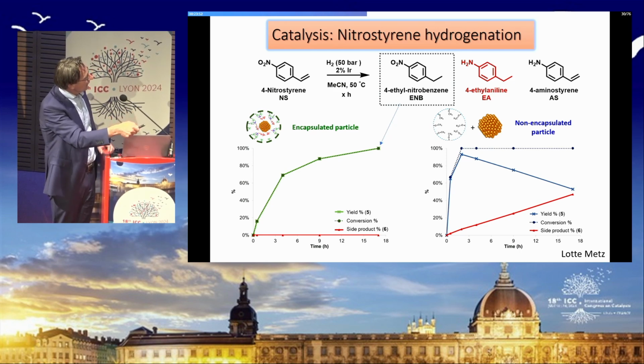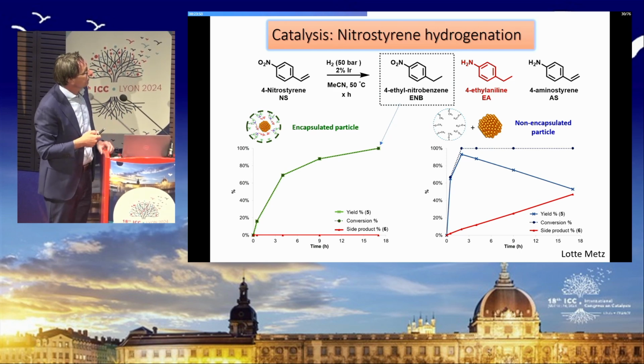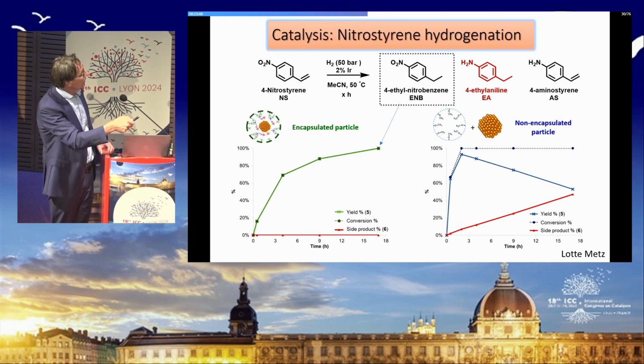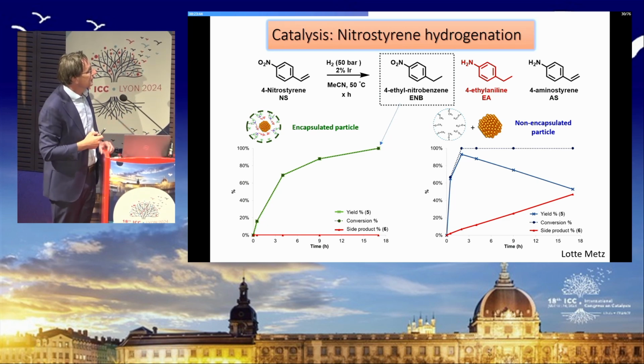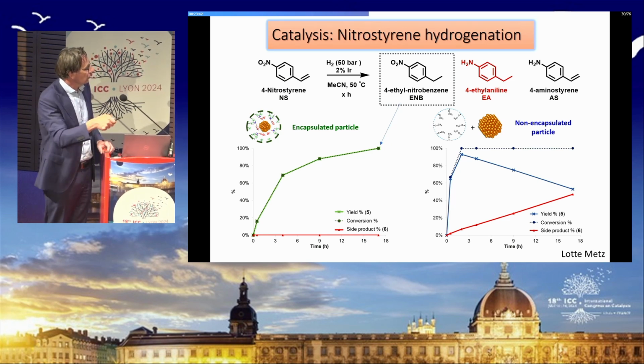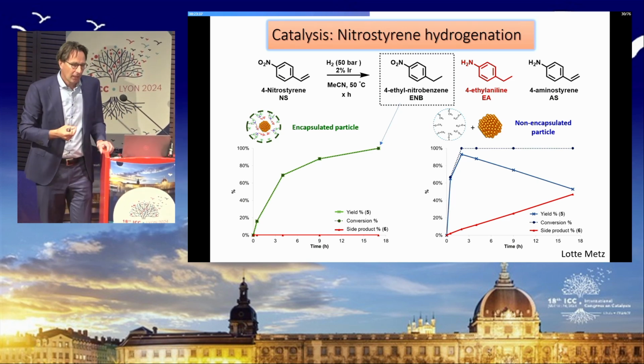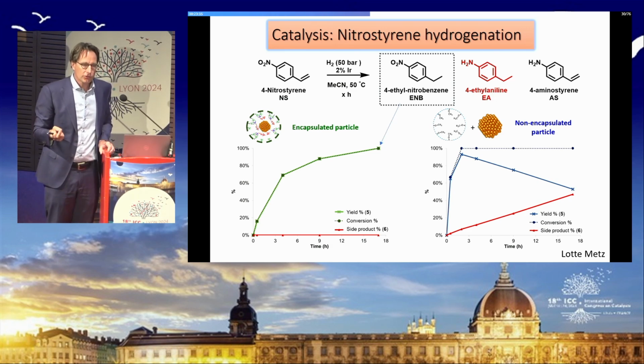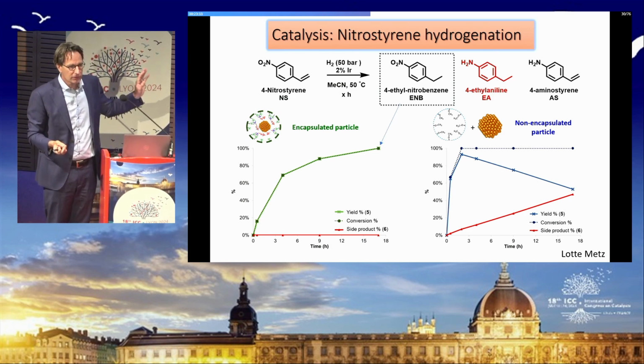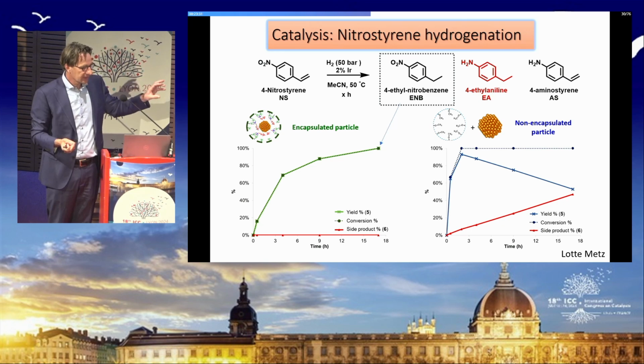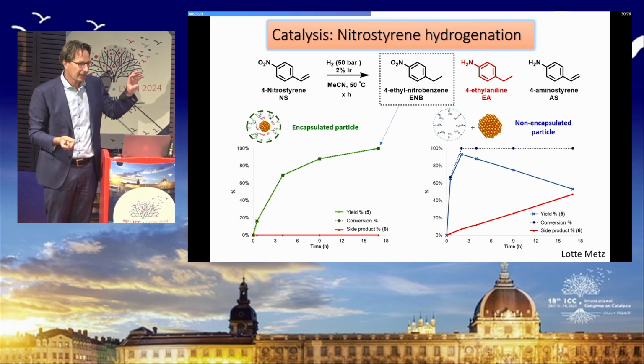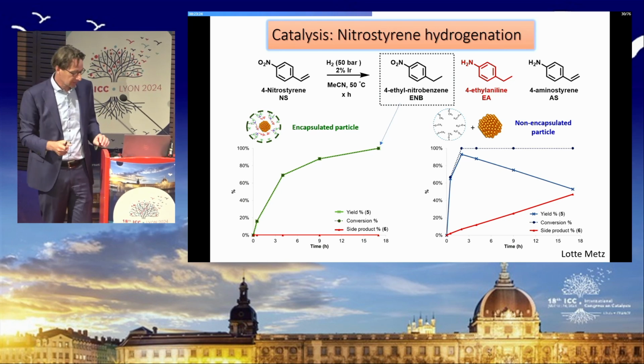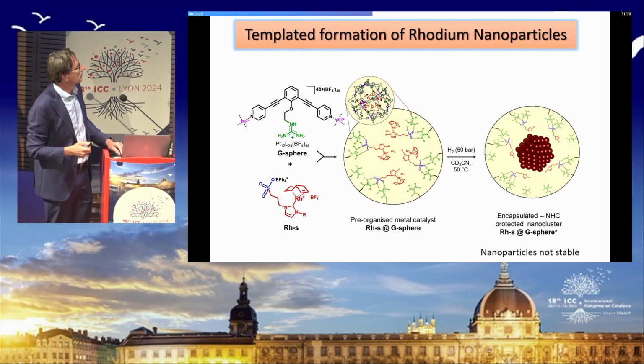If we look at the non-encapsulated particle as a reference, we see also this product, but this is over-hydrogenated to ethyl aniline. So here you can see byproduct formation. So this reaction itself may be not so important, but clearly it shows that we can make nanoparticles inside these nano cages, and that these nanoparticles have different properties compared to the nanoparticles formed outside the cage.